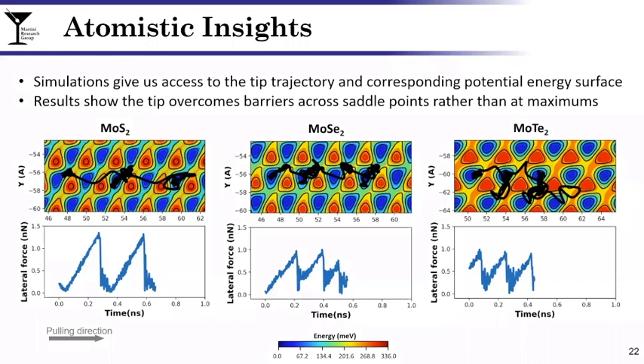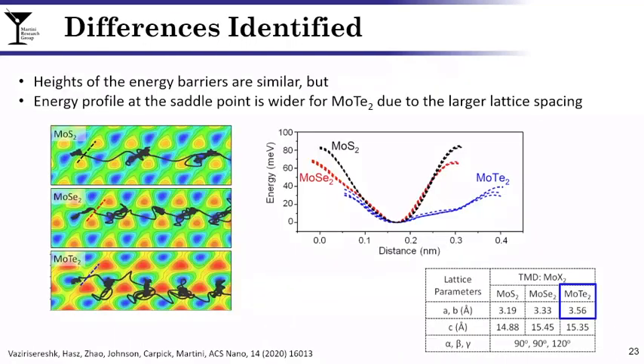We then compared directly the energy at the saddle points. So on the far left, you're looking again at those potential energy surfaces. The black lines are the tip trajectories, and we analyzed the energy at the position where the tip actually moved. And you can see in the middle figure that even though the height of the barriers was about the same, for the MoTe2, the width of the saddle point was the largest. So this can be directly correlated to the fact that MoTe2 has the largest lattice spacing. So what we're seeing here is that among these three transition metal dichalcogenides, they have similar structures, similar energy barrier, but because of the width of the saddle caused by the lattice spacing, it's easier to move forward on MoTe2 and we have lower friction.